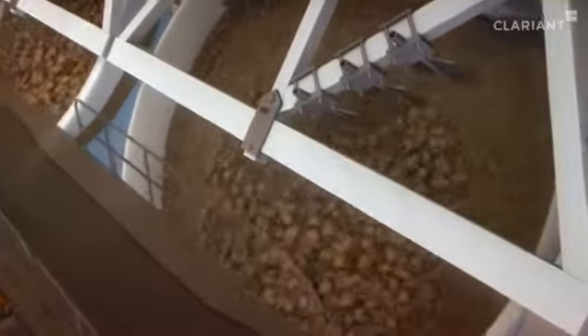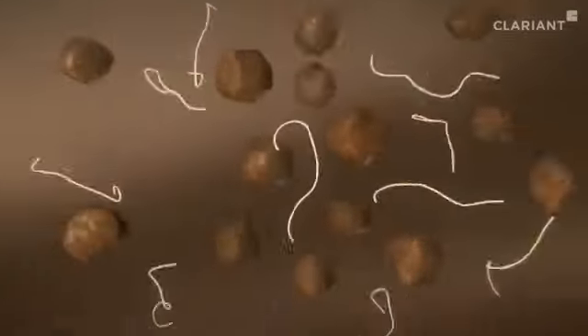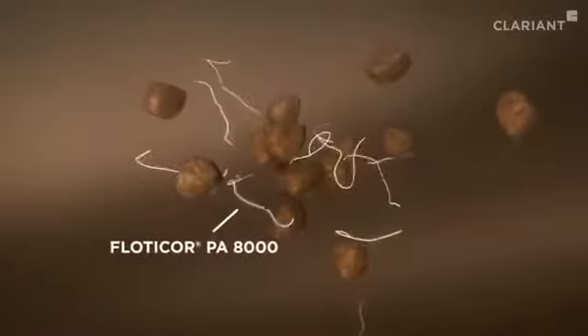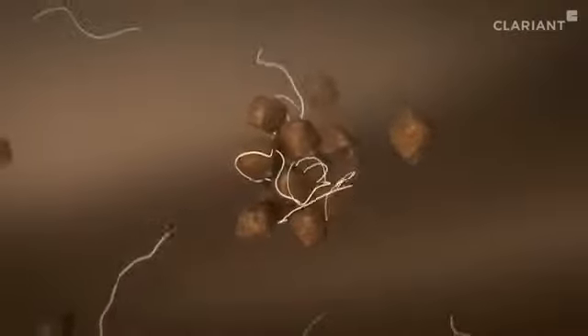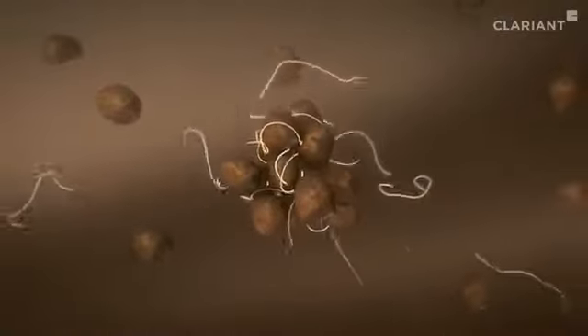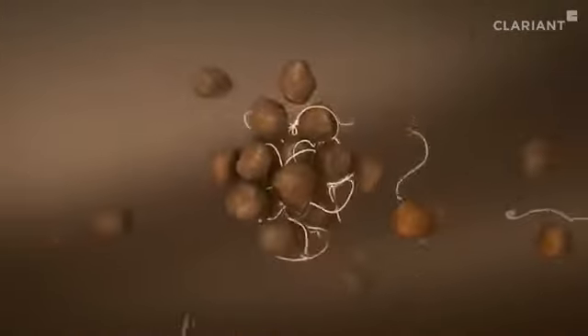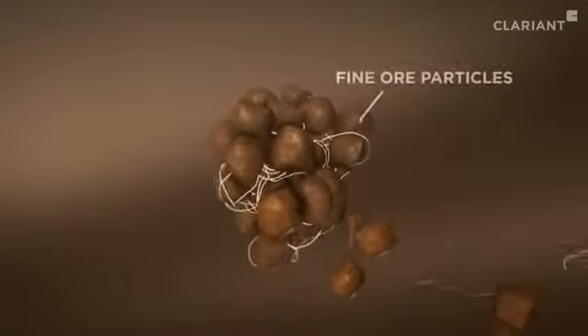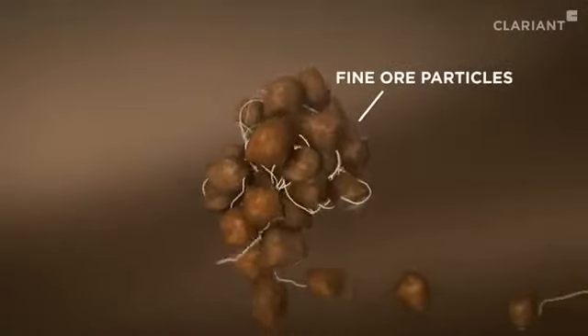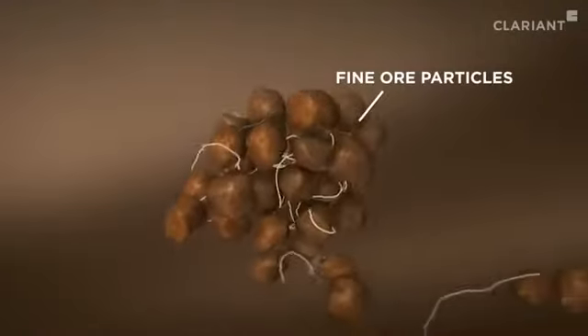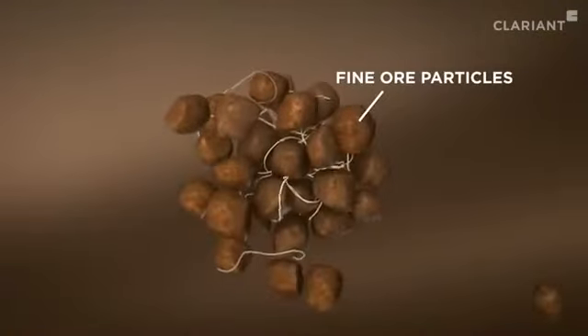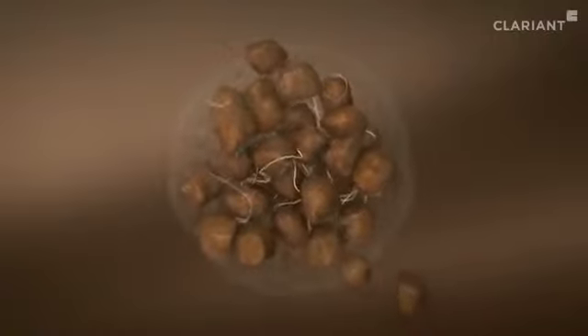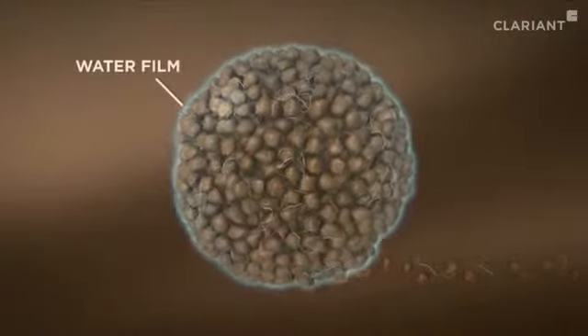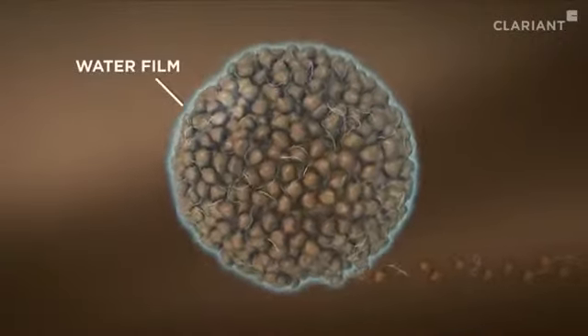Traditionally, binders like bentonite, which is a silica-containing natural clay, have been used for pelletizing. Now, using Clariant's Floticor PA8000, the amount of bentonite can be reduced by 70%. Clariant's additive helps very small iron ore particles, called microfines, travel through the wet slurry and be distributed evenly throughout the pellet. This forces out water and increases pellet compaction.